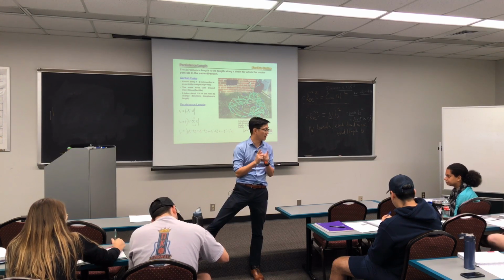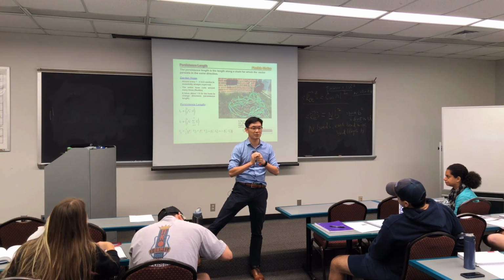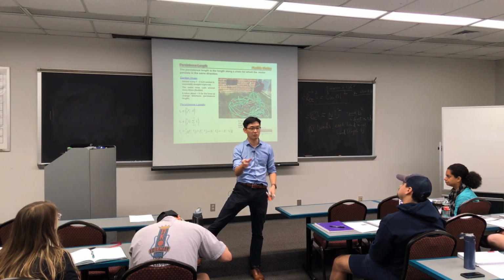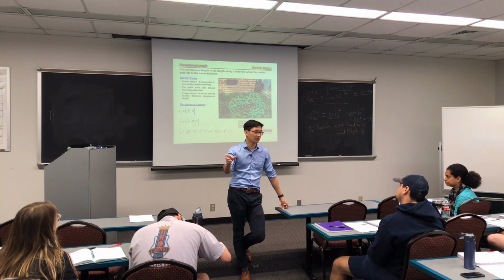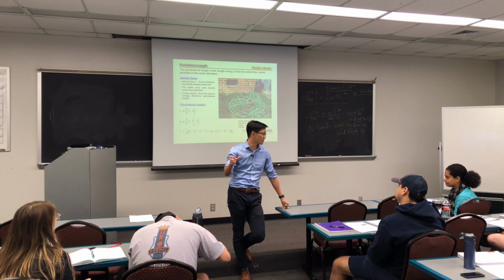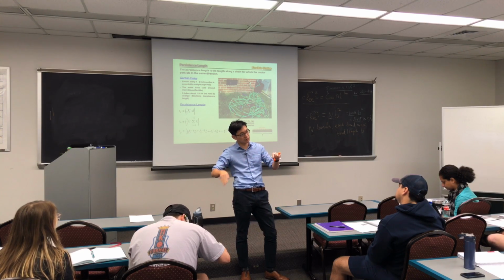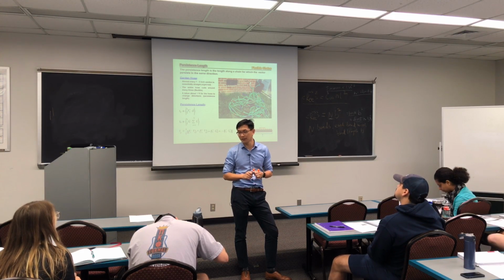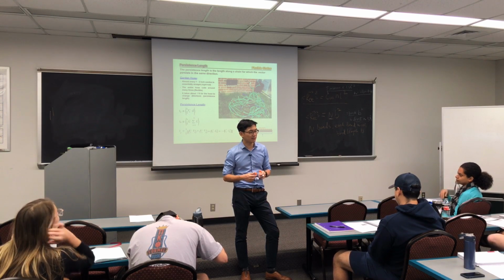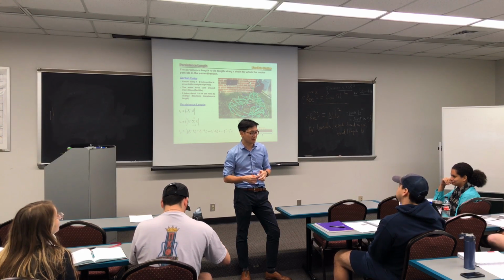So for a short chain of, let's say, my conjugated polymer, we said persistence length is 20 nanometers. If your contour length is short, or low molecular weight, locally they are quite rigid. But as you start to polymerize and make them longer and longer, once they reach a molecular weight of about 100 kilodaltons, you reach a contour length of about 50 or 60 nanometers. Then at this length scale, we will start to see chain bending, okay? So in the next class, I'm going to stop here. Some of you asked that you cannot fully understand the question in homework problem one. Now you should be able to understand most of it.